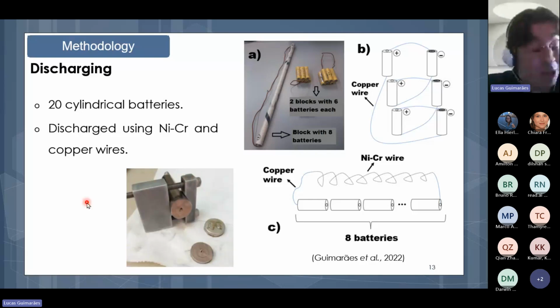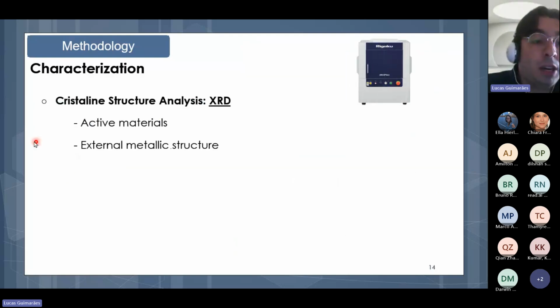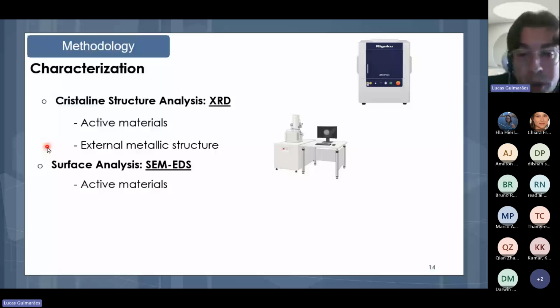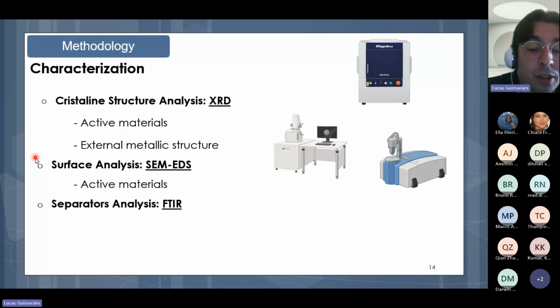And then for the characterization, one battery was cut open with a diamond blade and then manually opened, so the components could be characterized. For the characterization, we first used crystalline structure analysis via X-ray diffraction. The active materials underwent this kind of analysis, and the external metallic structure of the batteries as well. Later, we analyzed the surface of the active materials of the batteries with scanning electron microscopy. Then with Fourier transform infrared equipment, we analyzed the separators of the batteries.